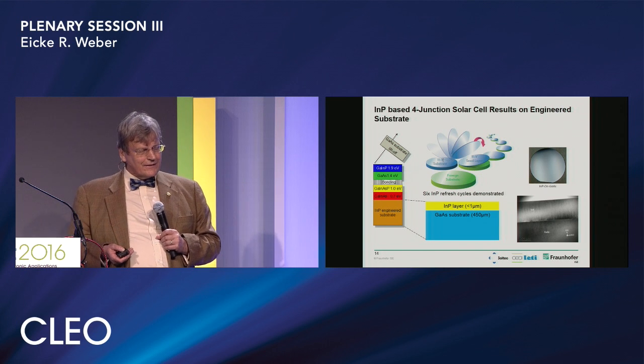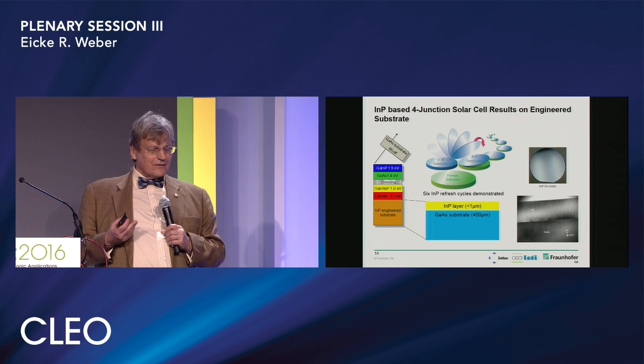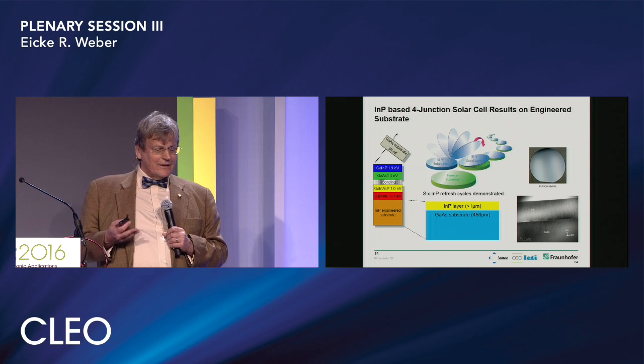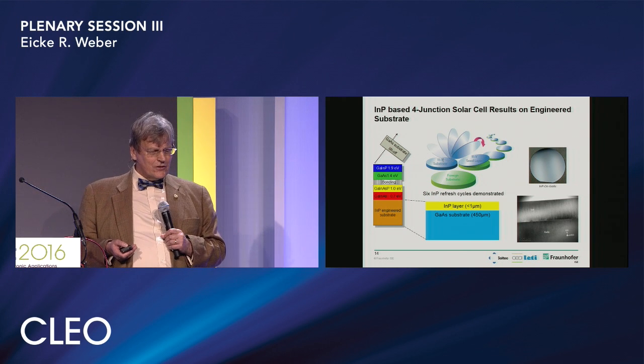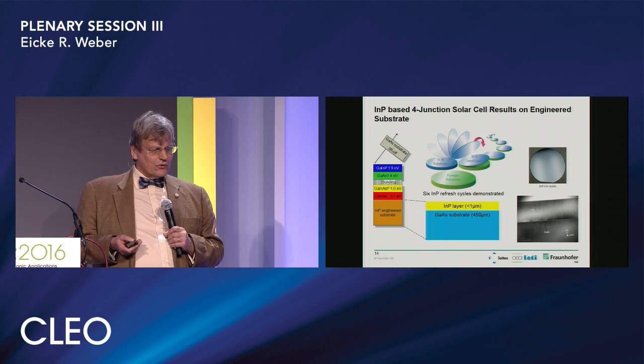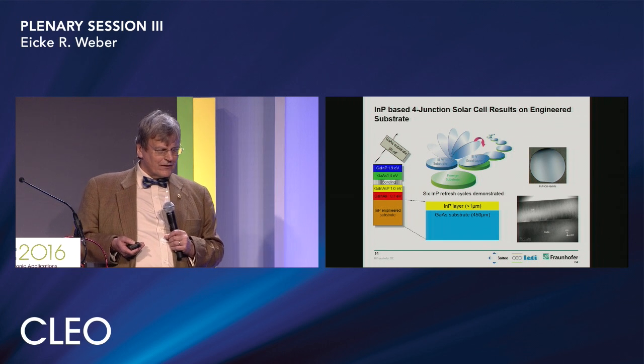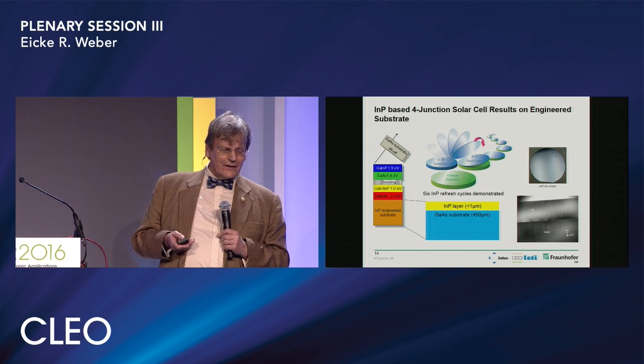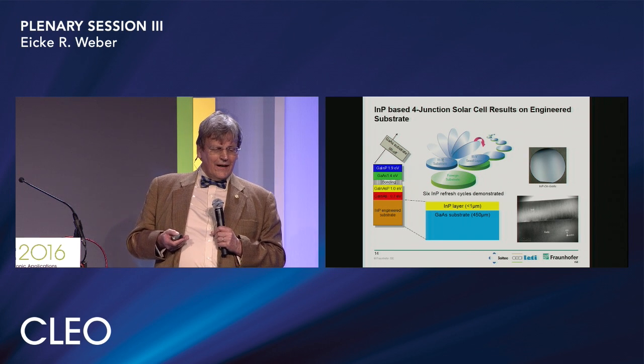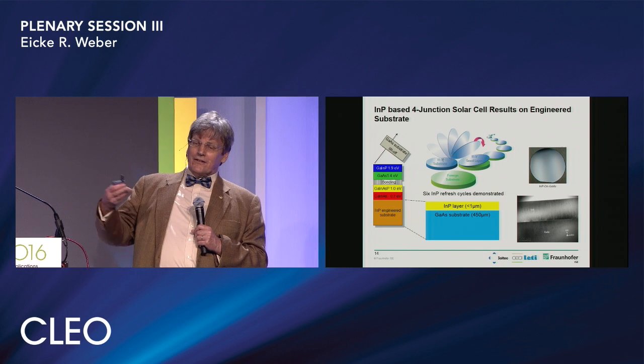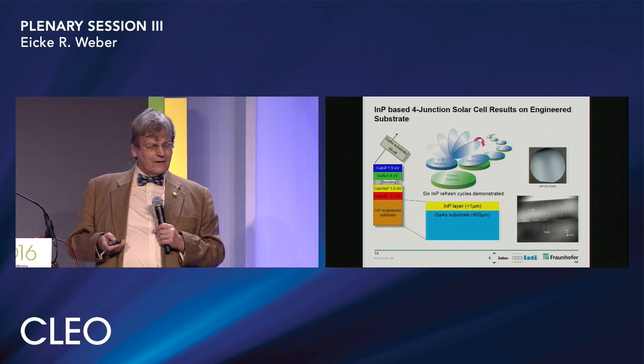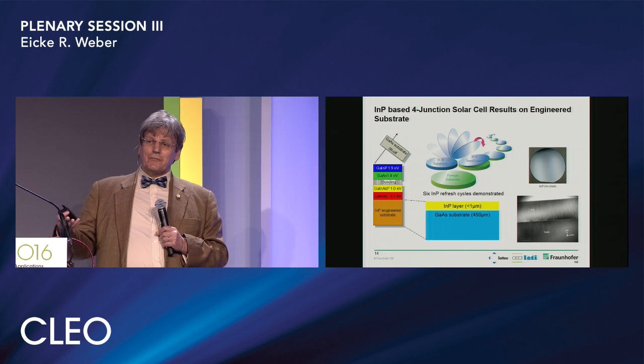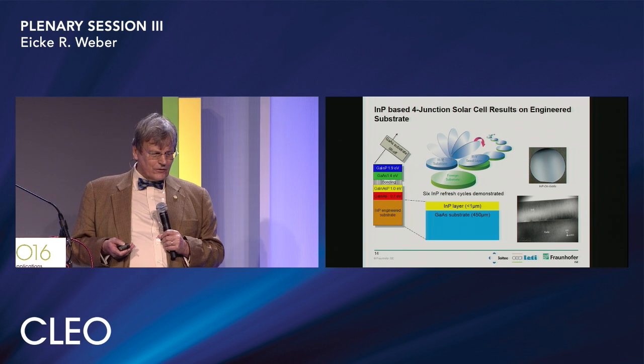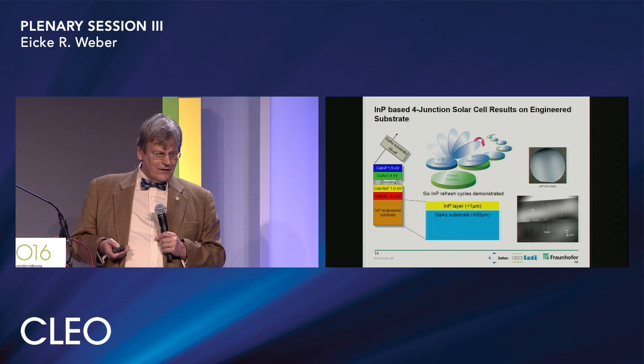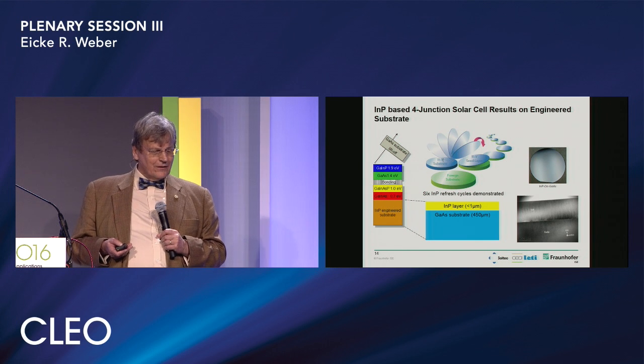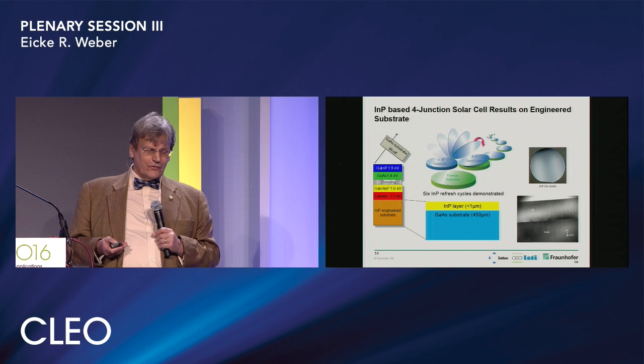The indium phosphide layer itself is not an indium phosphide substrate, but it is an indium phosphide on gallium arsenide engineered layer. And you see the two structures, gallium indium phosphide, gallium arsenide from one side, gallium indium arsenide phosphide, gallium indium arsenide on the other side, and then wafer bonded together, and one can even use the lift-off substrate on top several times for subsequent growth runs. And you see in the TEM cross-section, the right bottom part, how high is the quality of the interface.